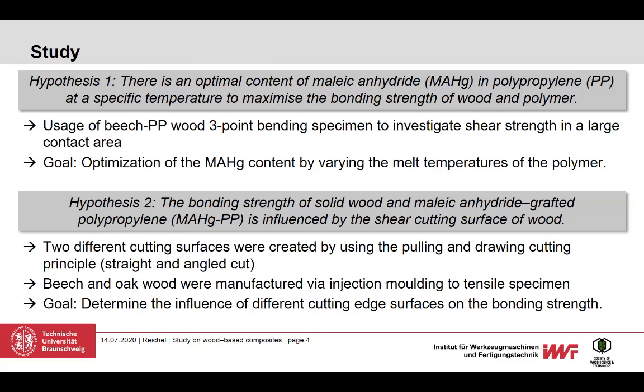Our study was split into two parts. The first one was to show the process parameters for the bonding agent we wanted to use, which is maleic anhydride grafted polypropylene. And we detected the influence of the melt temperature and the weight ratio or weight content in the polymer. The second one was to evaluate the influence of a shear cut surface of the wood component on the bonding strength of the overall hybrid component, which was done by using tensile specimens. In the following, I want to show the results of these two investigations.